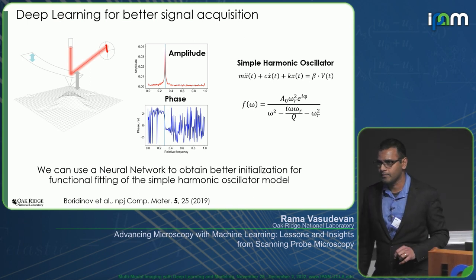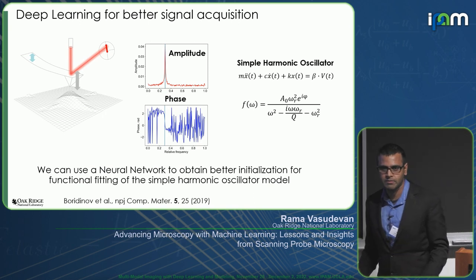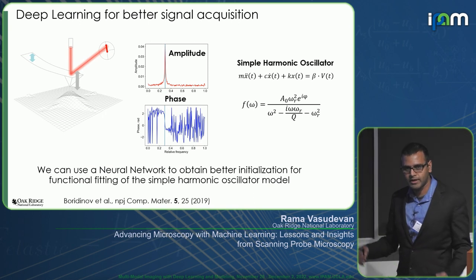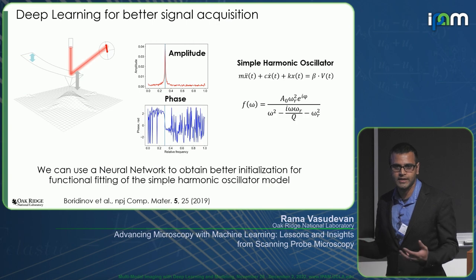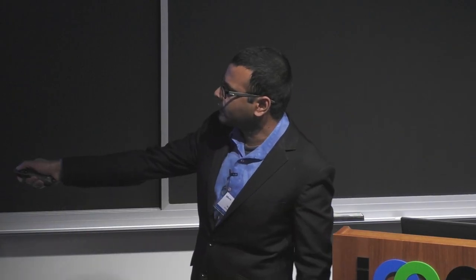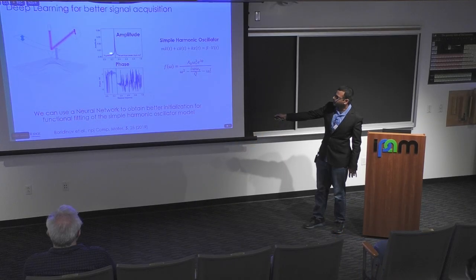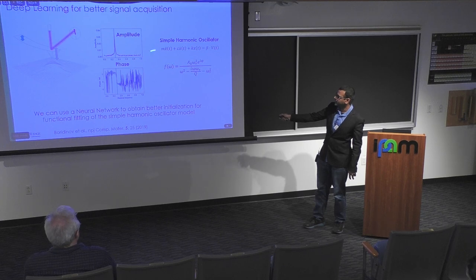As I mentioned before, in order for us to be able to interpret signals that are coming from the AFM, very often if we are working in some kind of resonant mode, then we need to understand the cantilever dynamics, right? So you have this cantilever that's resonating on the sample surface, and typically we have to choose a model, and that model might be a very simple model, like a simple harmonic oscillator model. This is a linear system, and it's very easy to solve. And so we can take our data that comes from our AFM, and we can find these fitting parameters for the simple harmonic oscillator model, right?